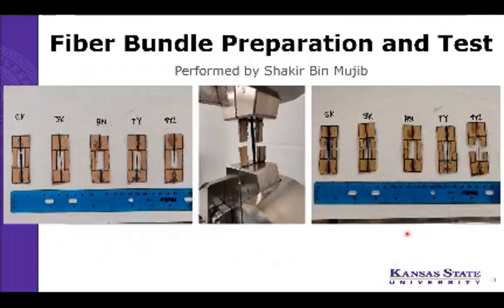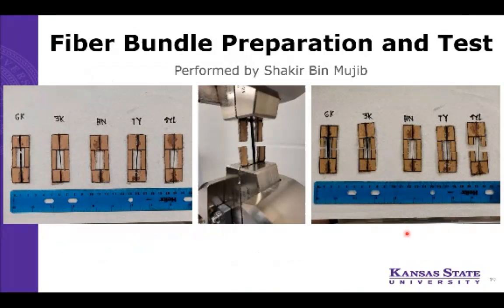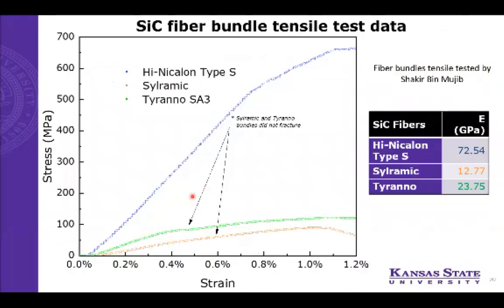One of our graduate students, Shakir Bin Mujib, has also performed some fiber bundle testing following a procedure described in literature. Here we can see some Hi-Nicalon, Tyranno, and Sylramic samples. They get pulled by the tensile tester here, and we got some data from that. So here we can see that data. The Hi-Nicalon Type S showed 72.54 gigapascal, followed by the Tyranno SA3 and the Sylramic. However, the Sylramic and Tyranno bundles did not fracture entirely across their bundles. So I'm not entirely sure that a true comparison can be made from this, but it is worth looking at and considering anyway.